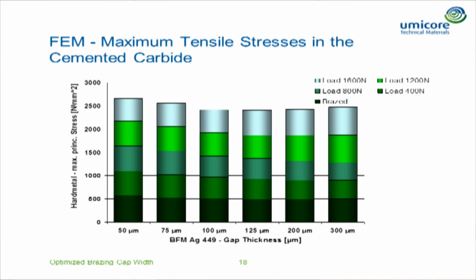On the x-axis, we have the different gap sizes, gap thicknesses. And the dark green color is the maximum tensile stresses in the cemented carbide. This is where we're looking now. After brazing, there's not a big difference in between. But then when we add the simulation load to the part, we can see that the stresses in the cemented carbide decrease at around 100 microns, and then slightly increase again.